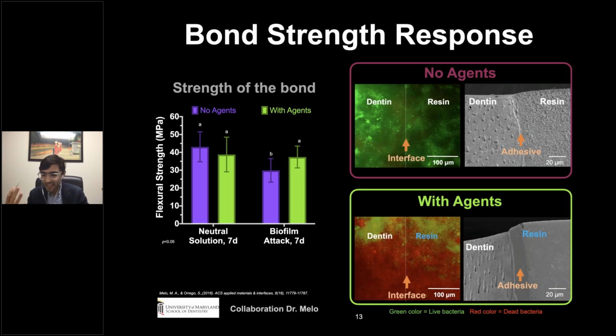Now, when we try to look for the same features with the agents, we see a very flat, polished resin surface. We clearly see the distinction with the adhesive, right? We see the adhesive layer and resin. This tells us it was more clean.